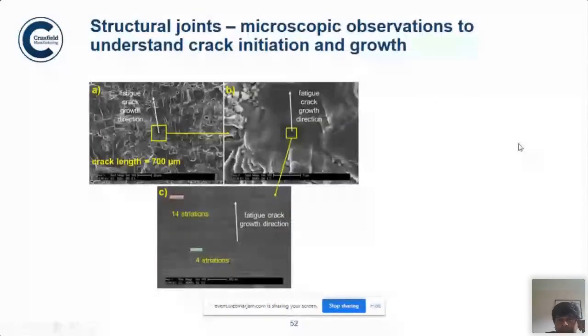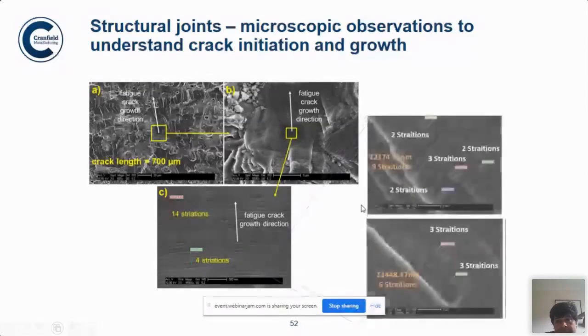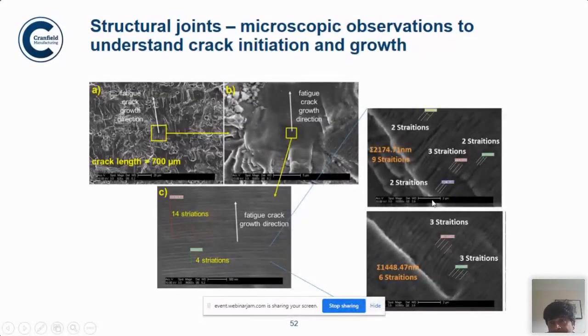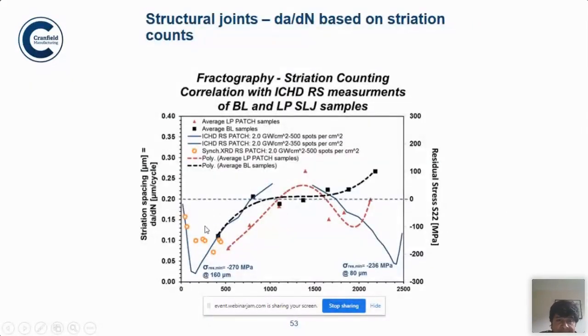And when we measure the fatigue striation spacing in SEM, because striation spacing basically gives you the crack propagation rate, the da/dN. Now, when we measure this, we clearly see... So please follow this particular red line. Here, there is a lot of data in this particular graph.